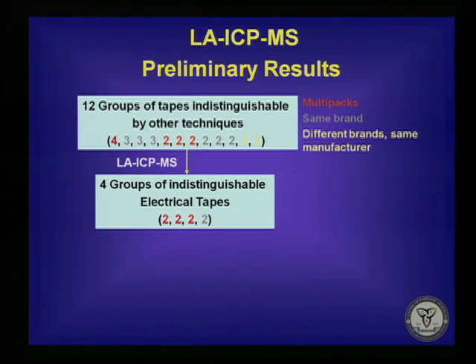3 of those groups were multi-packs, and 1 was of the same brand. The result that surprised us the most was discriminating the multi-pack of 4 tapes. And again, that multi-pack of 4 tapes was part of a rainbow pack that had 6 color tapes in that pack. So I'm not sure how that rainbow pack was assembled and whether those 4 tapes were actually from the same batch or not. Most of these discriminations were done based on more than 1 element. 2 of the pairs were discriminated based only on 1 element. The preliminary results look very promising.